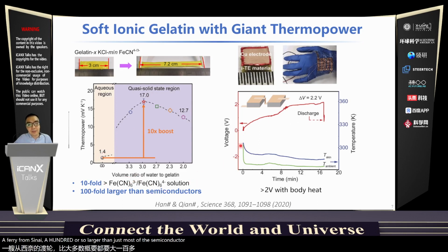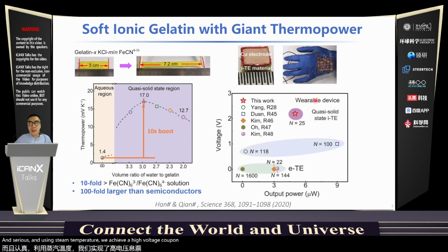We also fabricated a glove containing 25 of these ionic thermoelectric modules in series. Using skin temperature, we achieve a high voltage of 2.2 volts. Compared with other semiconductors, our voltage is higher, but uses a much smaller number of ionic thermoelectric modules. So this work provides a strategy to boost thermal power and to harvest the small temperature difference between the body heat and the environment.